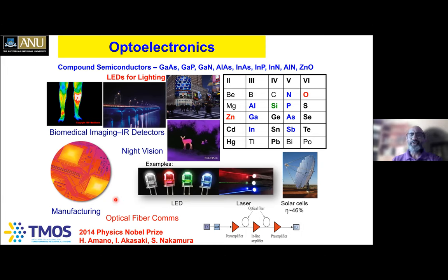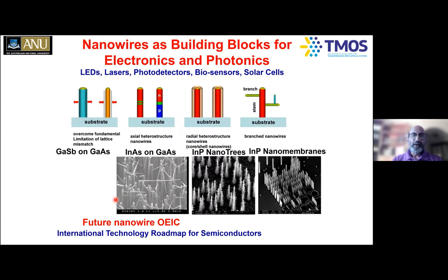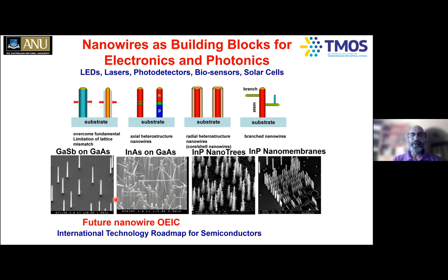The nanowires are nanostructures. Nanowires are seen as building blocks for the next generation electronics and photonics. One of the unique things with the nanowires is that you can really make nanowires of any material on any substrate without the worry about the lattice constant differences between the substrate and the nanowire which are really growing. Because of their nanostructures, either they can expand or contract if these lattice constants are larger or smaller than the substrate lattice constant, for example. Lattice constant is a unit cell of the crystal which really repeats itself in all three dimensions in a crystal.